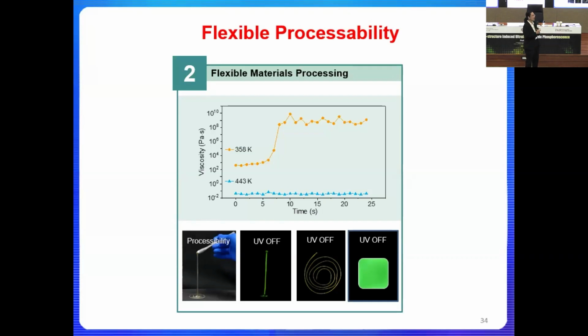So what is needed now is to find a host material so that we can allow phosphorescent molecules to be processable for all different applications. All right, so that drives us to look into the matrix for the phosphorescent molecules. So in this case, I would like to introduce one of the matrices, which is a small molecule. And the small molecule is special. It can form a glassy state. All right, that allows us to process. So we can process these phosphorescent systems by drawing, coiling, and forming, right? And what we control here is the temperature-dependent fluidity of the small molecule.